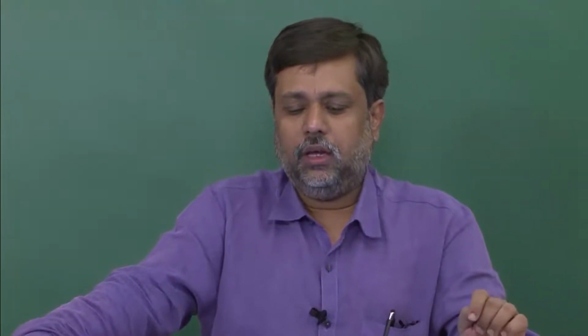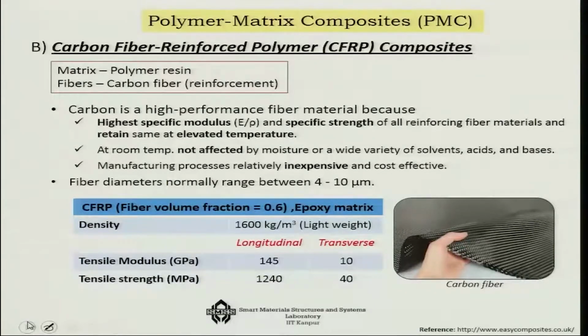Now, carbon is a very high performance fiber in comparison to glass fiber. It has very high specific modulus, the E/ρ ratio, that is the modulus of elasticity to density ratio, and also a very high specific strength. Not only that, it can retain the same at elevated temperature. GFRP by 200 degrees centigrade is of no use, whereas CFRP can be used to a much higher temperature. And at room temperature, it is not affected by moisture or a wide variety of solvents, acids and bases. But it is expensive, particularly the carbon fibers are expensive.